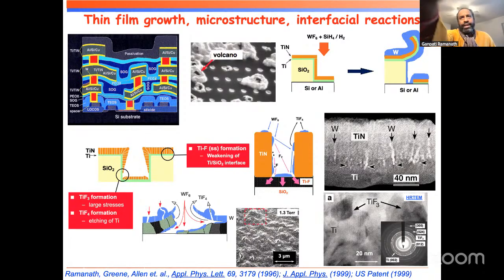I'm showing some schematics here. These are all drawings that I had made at that time. And every single aspect of it was based upon microscopy and spectroscopy. I've shown 2 images on the right-hand side, which is catching the tungsten diffusing through the porous layer in the act. This was quite a cool image at that time. You can see the bright regions marked tungsten actually have the same orientation as the porosity shown schematically on the left. And then you had TiF3 formation, which is stressing.